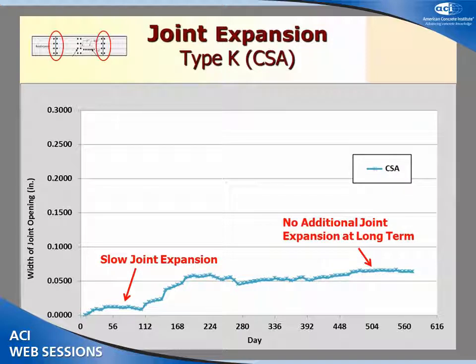And now you can see the joint expansion for type K calcium sulfoaluminate. There is a very slow joint expansion at the early age, and we almost didn't notice any additional joint expansion after a long term.